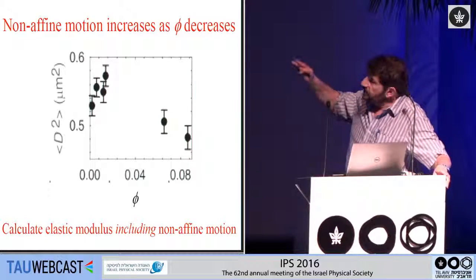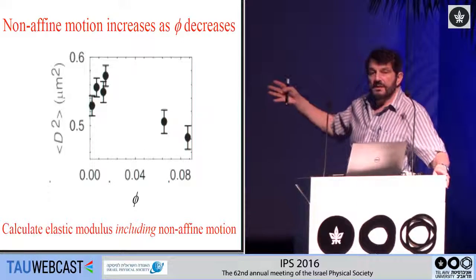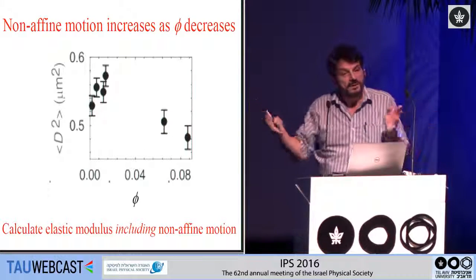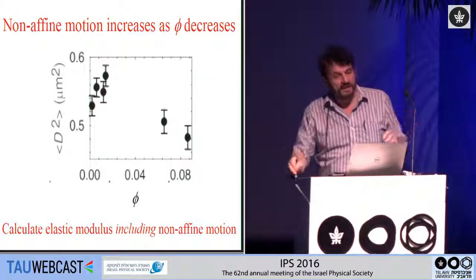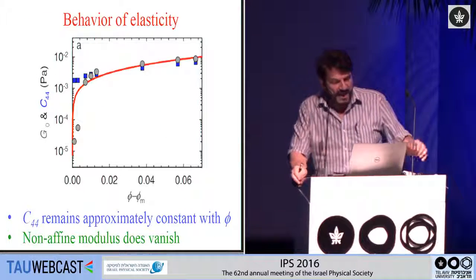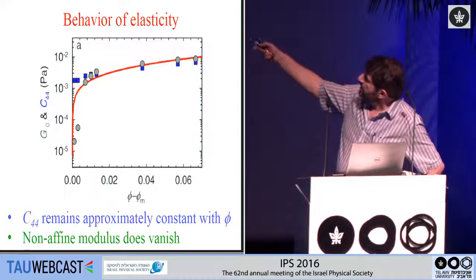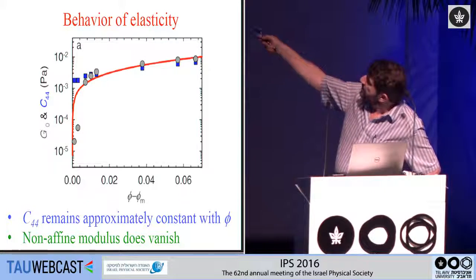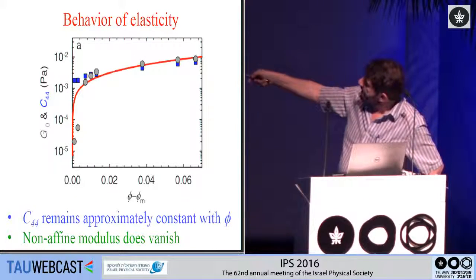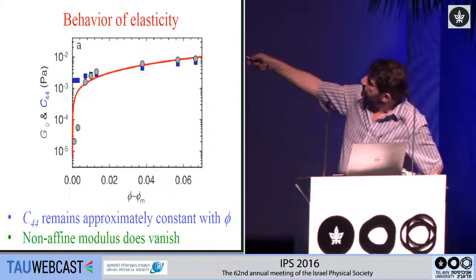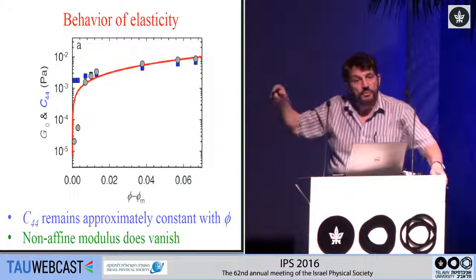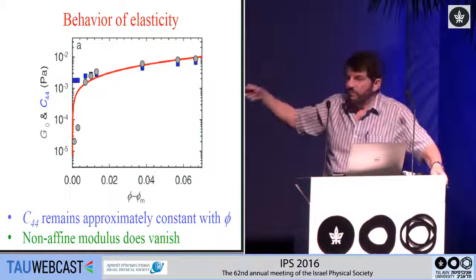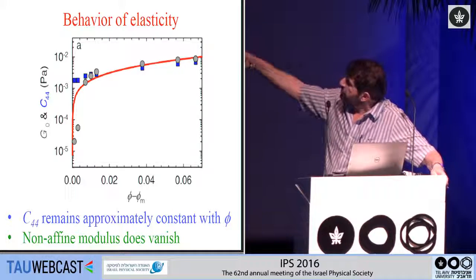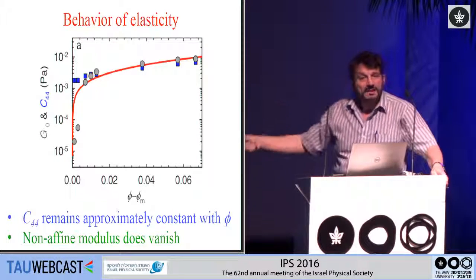This is exactly what you would expect. So what you have to do is recalculate the elastic modulus. You can no longer use the linear calculation for the elastic modulus. And when you recalculate it, this is the Born calculation as a function of volume fraction. When you include the recalculated non-affine region, you see exactly what you measure. You see this melting behavior.